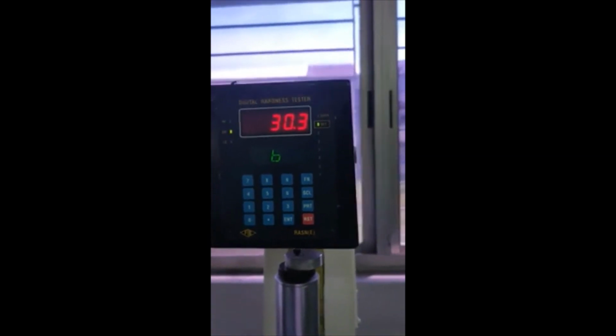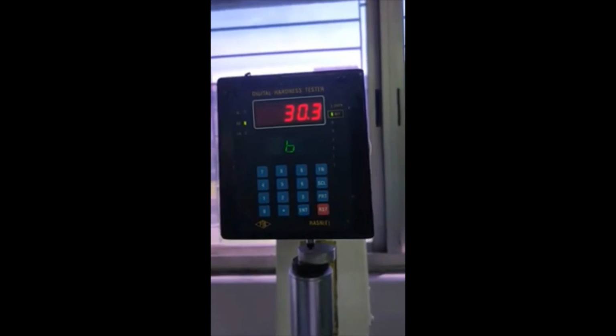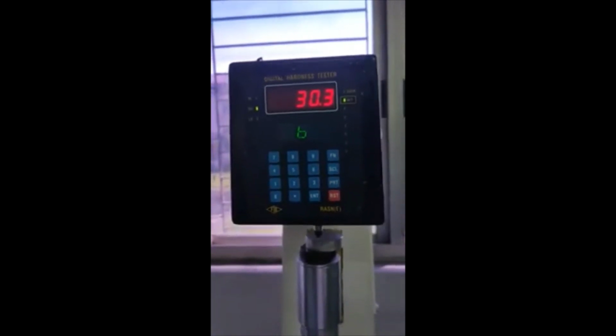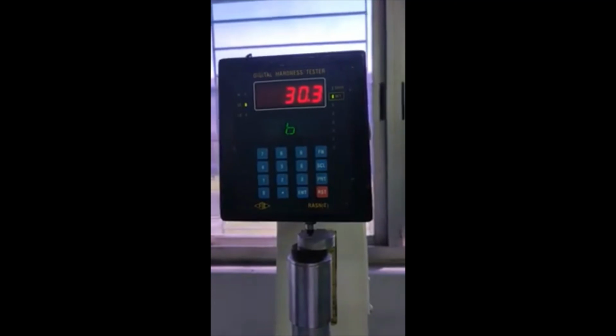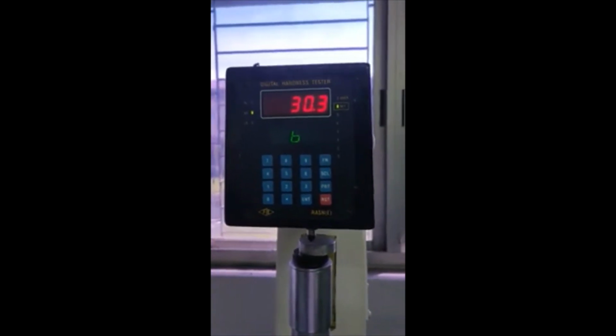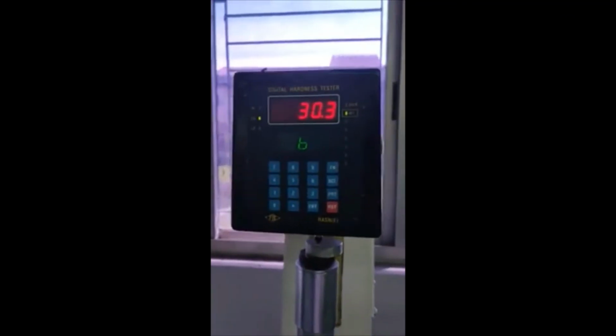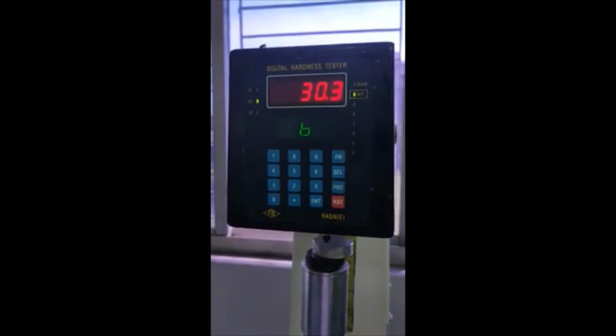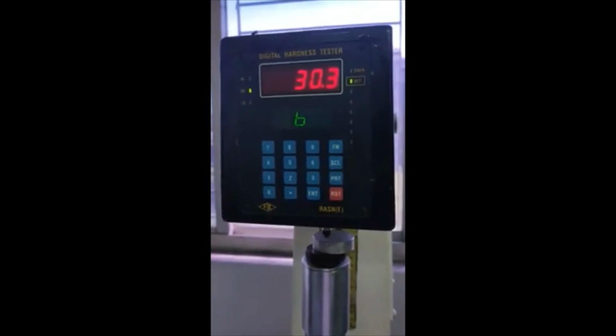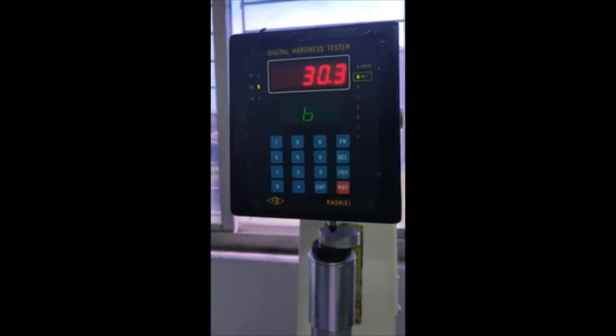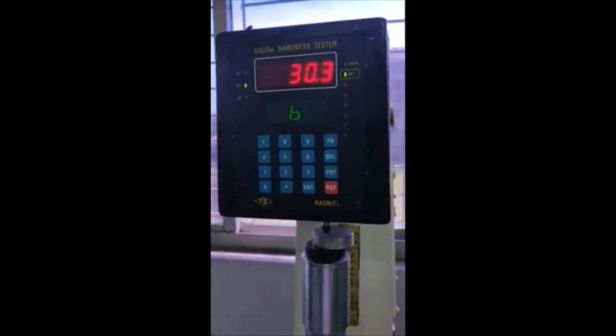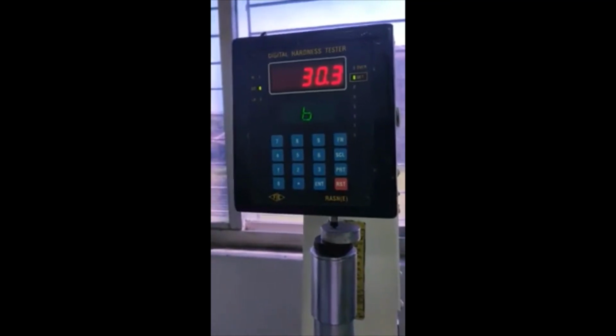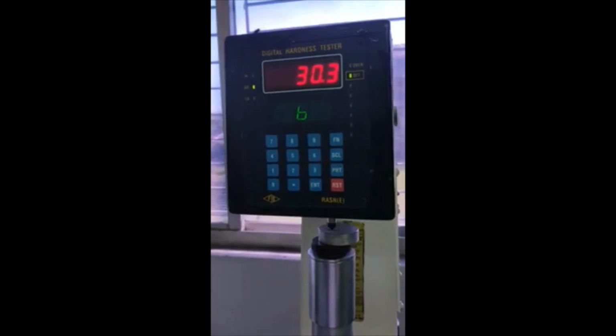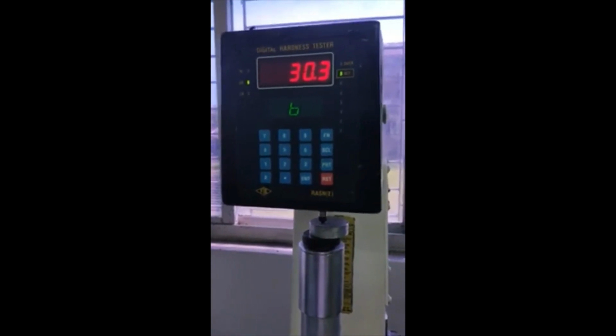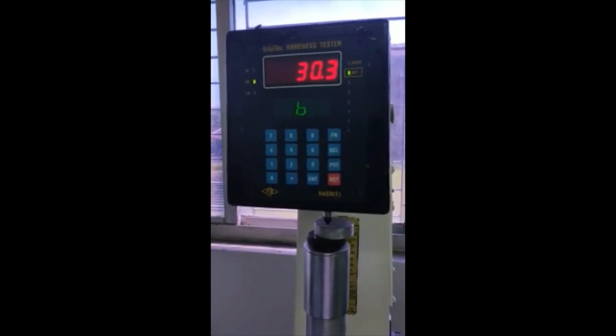This is 30.3. Generally for different grades of aluminum, hardness values are different. For commercial aluminum, the hardness value generally ranges from 28, 29 to 40 in digital hardness reading. This way we need to take 5-6 readings, and accordingly you need to put these values in your report. For Brinell and Vickers, you need to do your own calculations, but here you need not do these calculations. Automatically these values will appear here in the digital hardness testing machine.